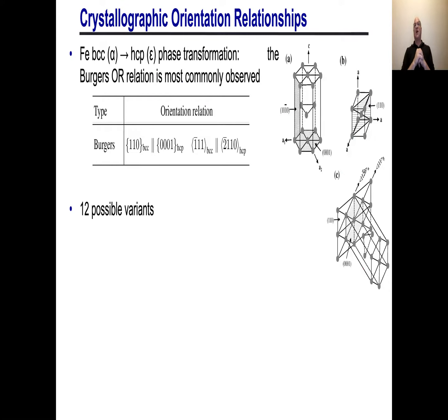Okay, so let's talk about some specific cases. I'm going to talk about the iron case, which is the alpha to epsilon phase transition, or BCC to HCP. The classic crystallographic orientation relation you see in these high pressure experiments is the Burgers relation. The Burgers orientation relationship is the one shown here. That is, the 110 plane of BCC, the high density plane, is parallel to the basal plane of the hexagonal material. And the 111 direction of BCC, the close-packed direction, is parallel to the 2-bar 110 in the HCP. So that's called the Burgers relation.